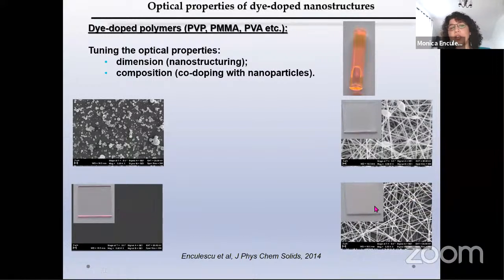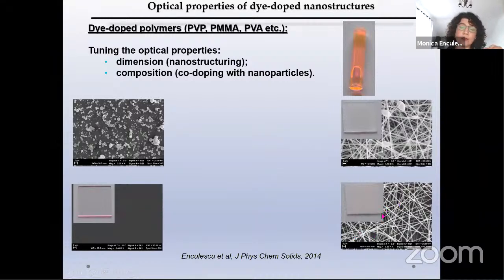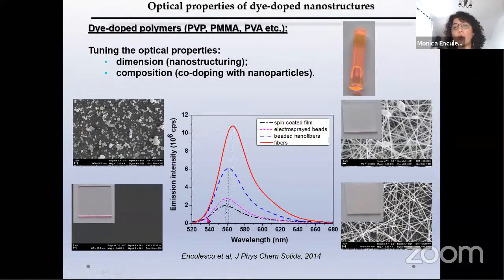And if we change further the parameters of the electrospinning, keep in mind that we have the same type of solution for all these four types of morphological composition, we can further go to uniform nanofibers. And what is interesting is that by changing the parameters of the electrospinning, we can obtain different types of morphologies for our nanostructures, but also we can obtain different optical response.